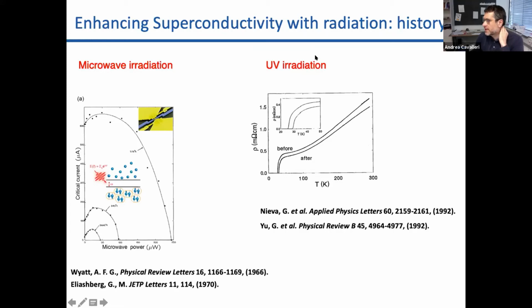There's also some work in the 90s where people irradiated underdoped cuprate materials with UV radiation and showed, primarily by way of annealing, although you can't really see this if you read those papers, that they achieved superconductivity as if the material was optimally doped. So they basically used these methods to improve the atomic and electronic structure of these materials.